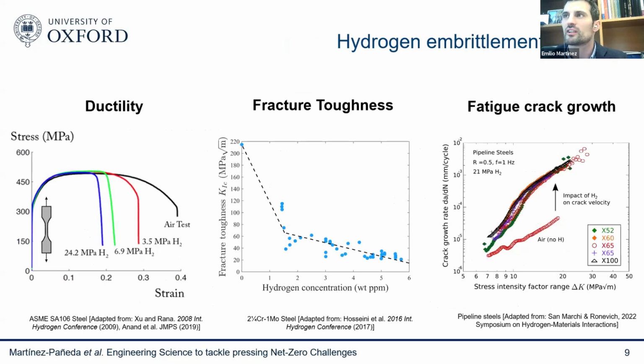You can see some examples here. For example, if you look at the left, this is ductility. These are stress-strain curves. I'm sure when you were students here, you did these stress-strain curves in the lab. This is part of the second year lab experiments these days. You take a piece of metal, and you expose this piece of metal to hydrogen. Hydrogen can come from a gaseous environment, like in this case, or it can come from water vapor, from the humidity, from seawater in a corrosive environment. But in one way or another, if you introduce hydrogen into your metallic sample, and then you do this kind of uniaxial tension test where you pull and measure the stress versus strain, force versus displacement, you see that if you introduce hydrogen into the sample, you very significantly reduce the ductility, the failure strain of those samples.